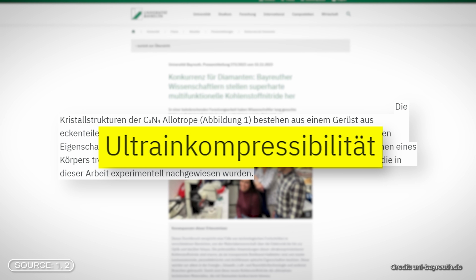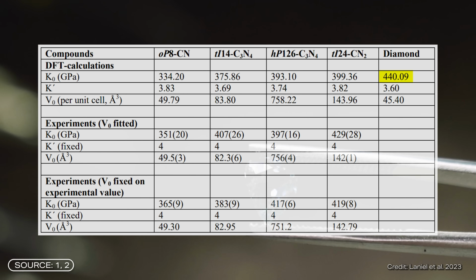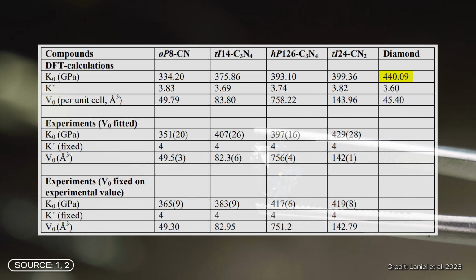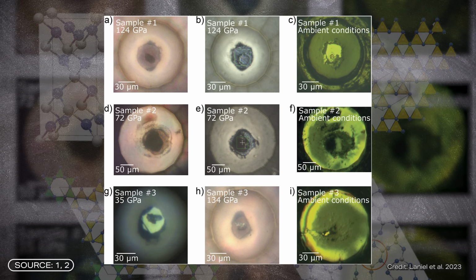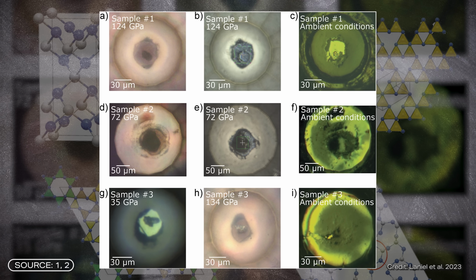The press release from the University of Bayreuth in Germany even refers to ultra incompressibility. This means that even under extremely high pressure, the volume of the material remains virtually the same because it cannot be compressed. But are carbon nitrides really harder than diamond in practice? We asked the University of Bayreuth about this, and the answer is quite interesting because it is no. Carbon nitrides come close in practical tests but do not exceed the 440 gigapascal that diamonds can withstand. This means that the 1989 prediction has not really been confirmed in practical tests. Nevertheless, we have a new ultra-hard material that can compete with diamonds in terms of application.